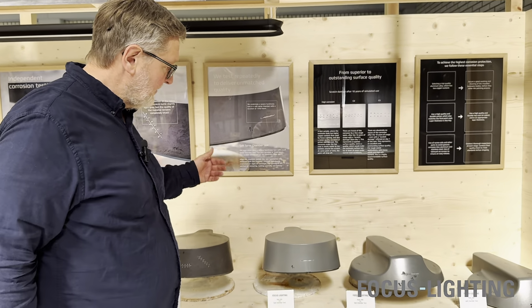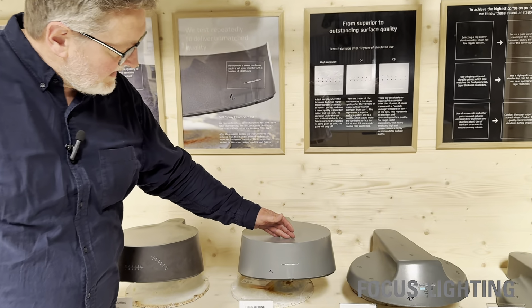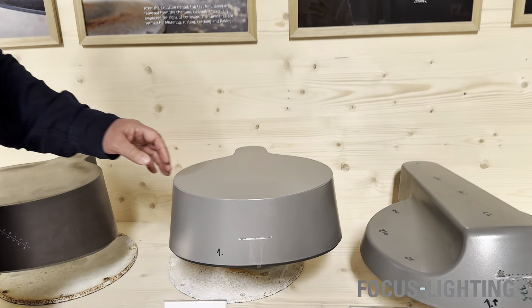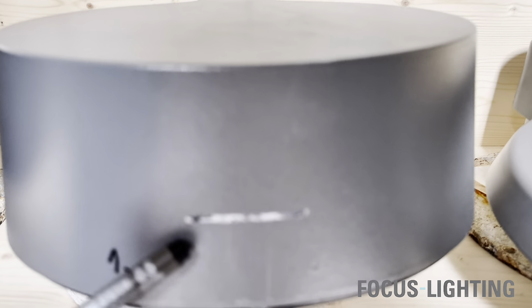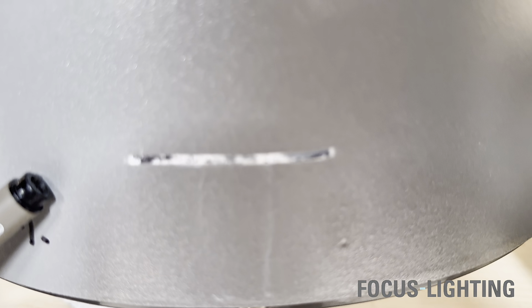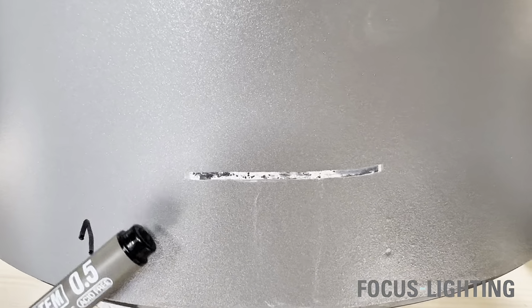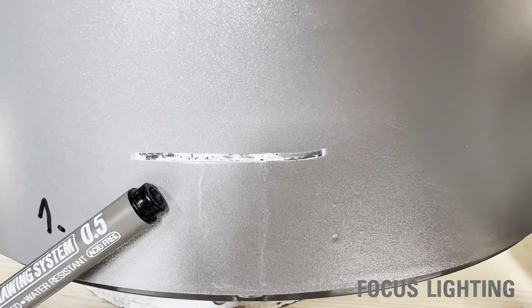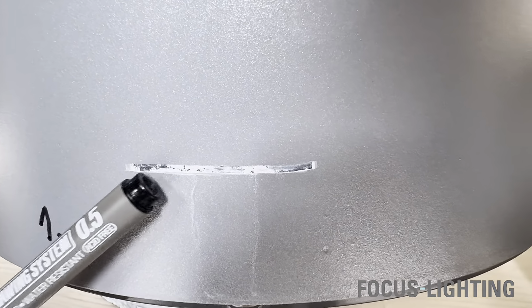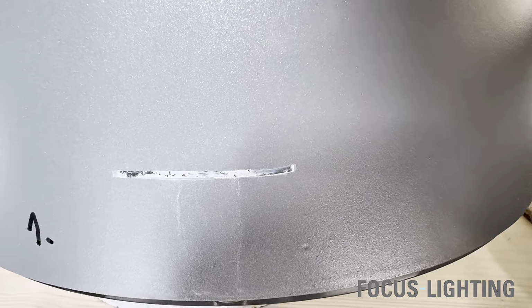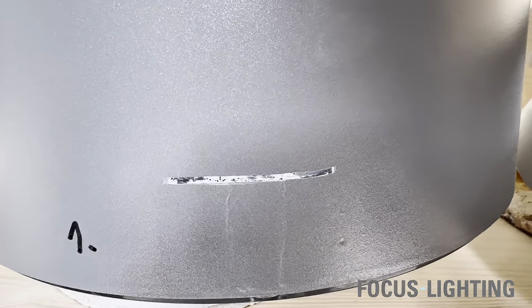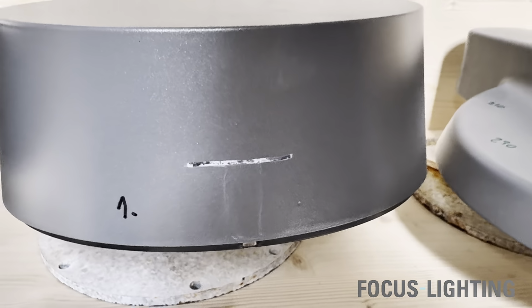Here we have the same housing as we saw on the C5. And if we move close to this one, again, look at the scratch. There's actually no blistering, there's no corrosion. You have the scratch which turns a little bit more white or grayish, but there's actually no loosening of surface coat. So this is extremely high quality of a surface protection.